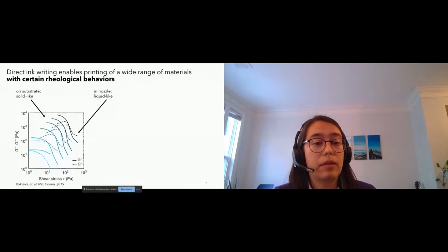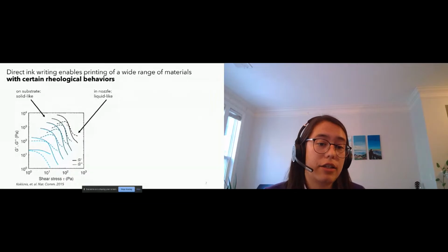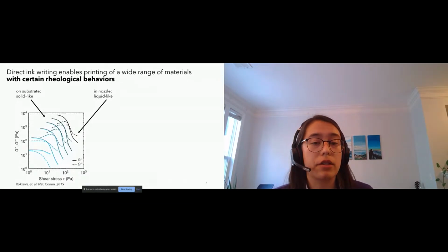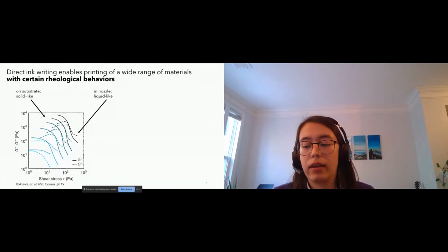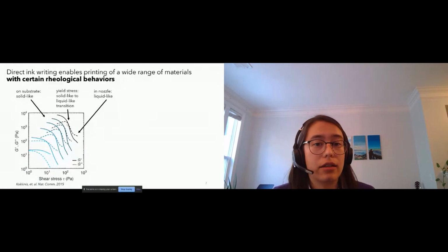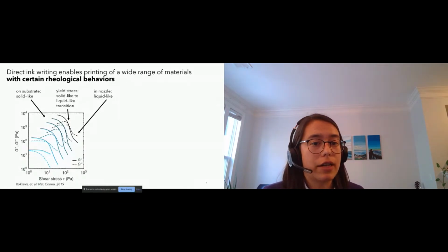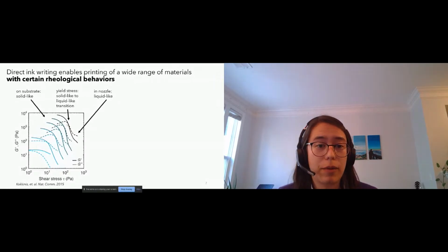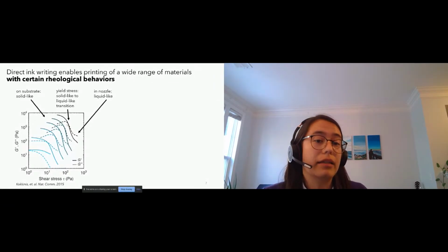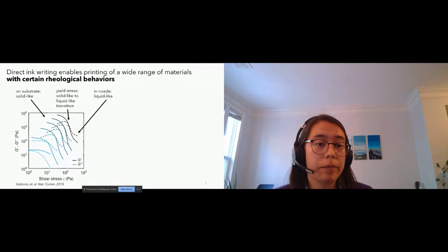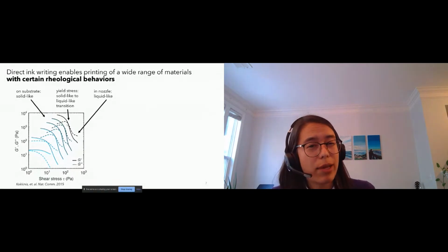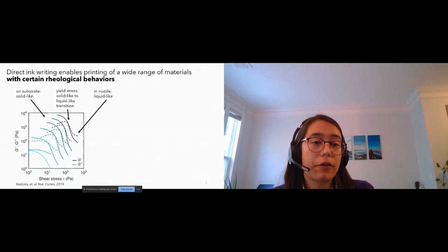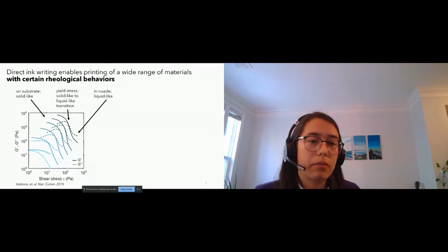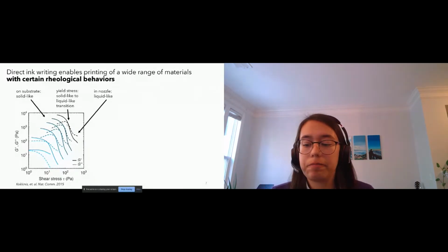Inside of the nozzle, we're going to be at high shear stresses, and you can see that G double prime is greater than G prime. So this material is going to behave like a liquid. And then in between that solid-like to liquid-like transition, there is a yield stress. So that's the stress at which this material stops behaving like an elastic solid and starts to behave like a liquid. That yield stress needs to be high enough that the material won't just collapse under its own weight. It won't just flow onto the substrate if you bump the stage or move the stage around.